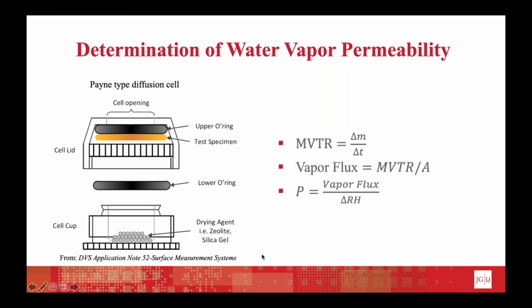To now calculate the permeability, we first need to know the moisture vapor transmission rate, which is the change in mass over the change of time. From this, we can calculate the vapor flux, which is the moisture vapor transition rate divided by the surface area of the Payne-type diffusion cell, which is 15.54 square millimeter. And then the permeability can be calculated by dividing the vapor flux by the difference in relative humidity from inside the cell and the environment.